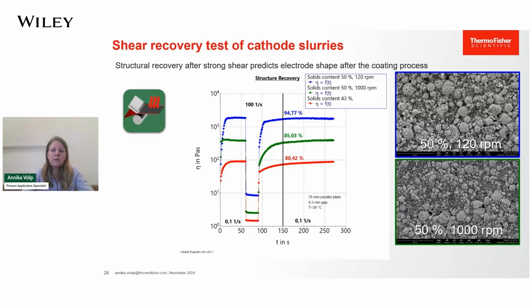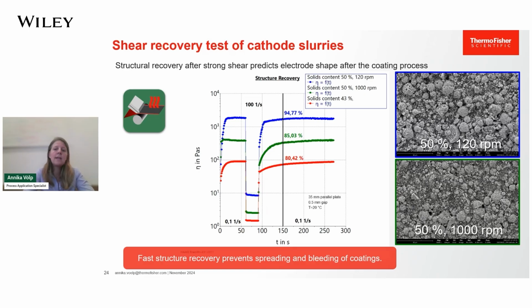The viscosity plotted versus time allows us to measure how quickly the viscosity recovers to its initial value before the exposure to the high shear. The faster the structural recovery, the less spreading and bleeding exhibited by the coating slurries.